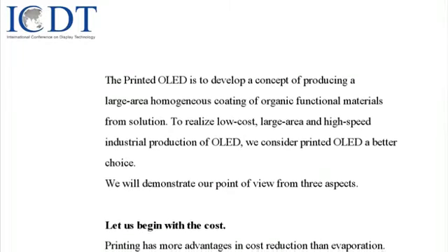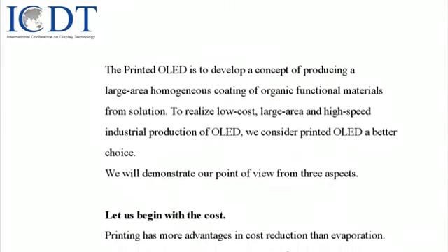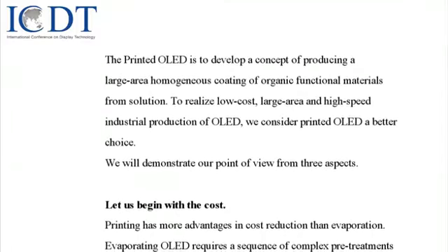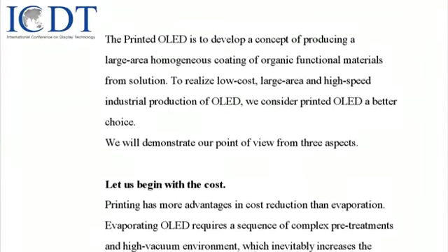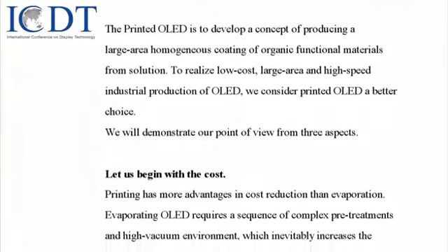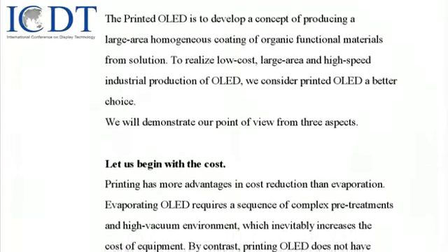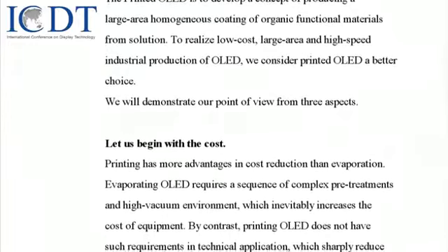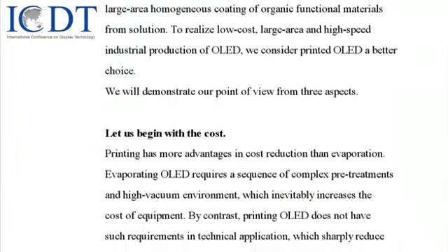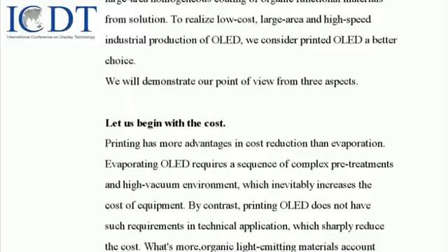Printing has more advantages in cost reduction than evaporation. Evaporating OLED requires a sequence of complex pretreatment and high vacuum environment, which inevitably increases the cost of equipment. By contrast, printing OLED does not have such requirements in technical application, which sharply reduces the cost.